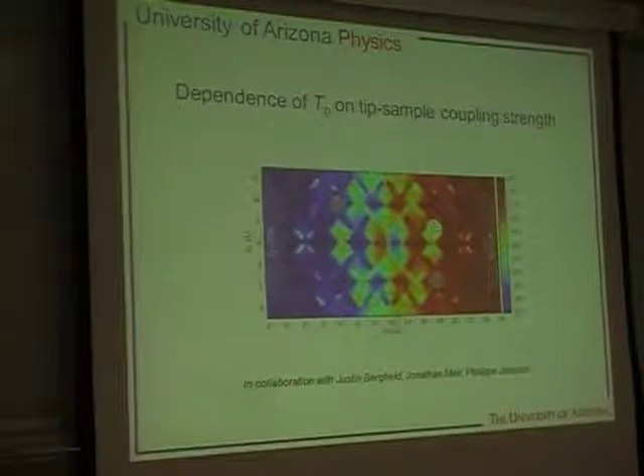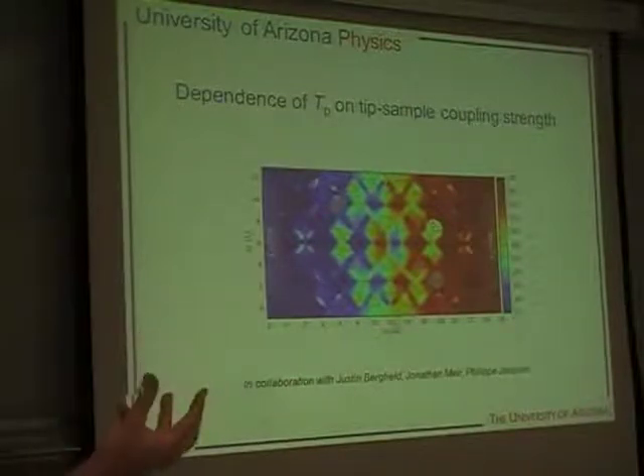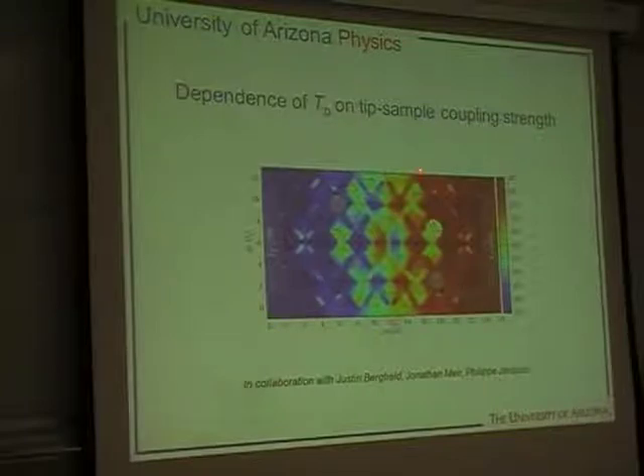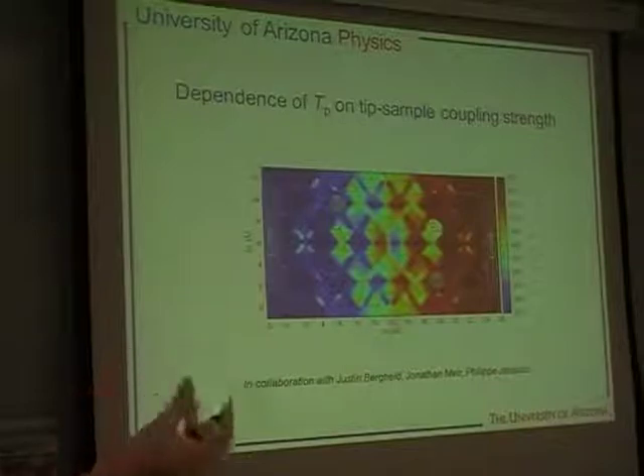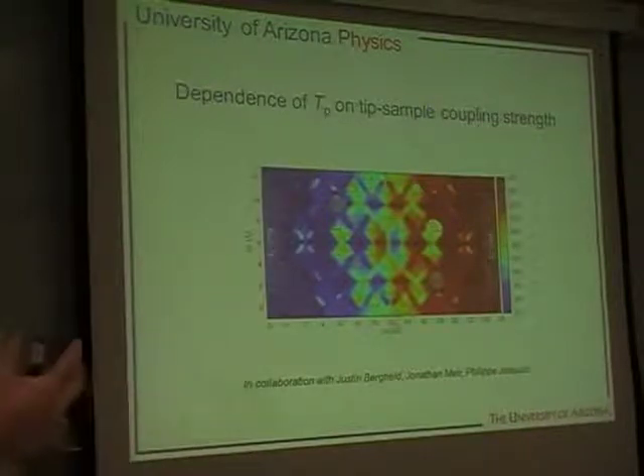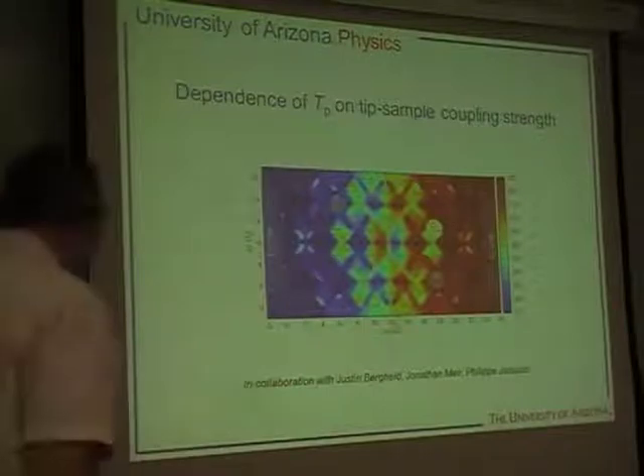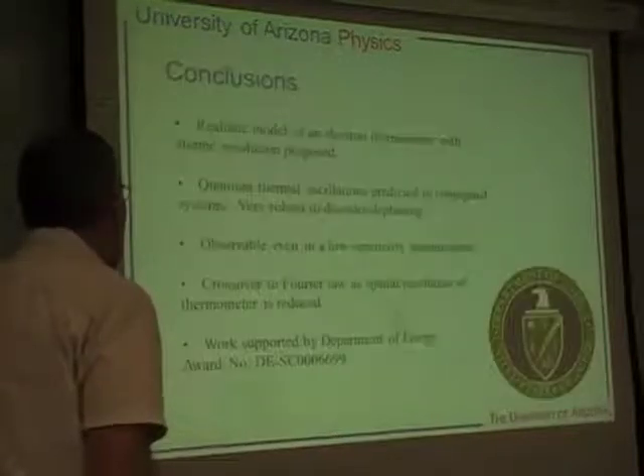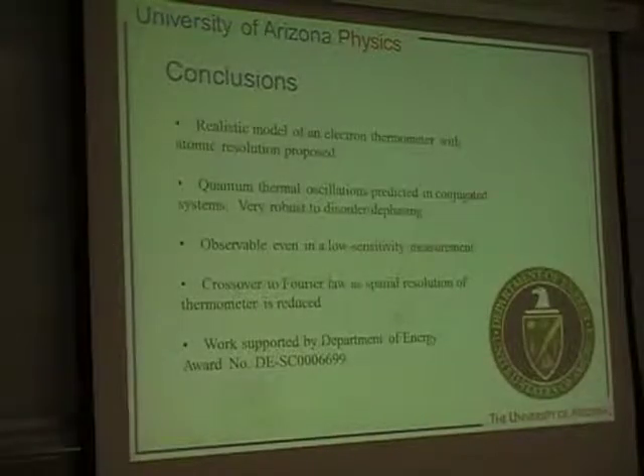Of course, the resolution of your image depends a lot on the nature of the tip, right? If it's an atomically sharp tip, you can get resolution like this. If it was a more blunt tip, of course, you wouldn't see something with such high resolution. So the measured temperature does depend on the nature of the tip, but does not depend strongly on, let's say, the size of the coupling to the tip. It does depend strongly on the resolution of that tip sample coupling. So that's all I wanted to say.